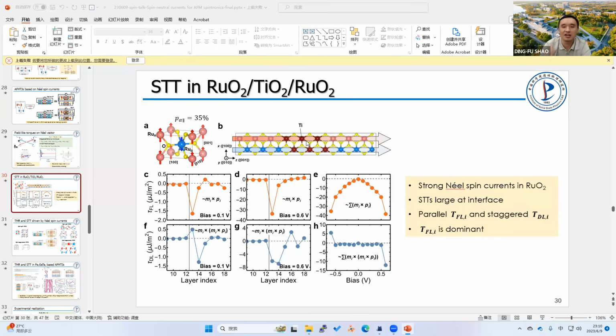In this case, I think the titanium oxide is the best, because the structure is exactly the same. The lattice mismatch is very small, so we can have a very good epitaxial structure to preserve the position of the sublattices in the two sides of the antiferromagnetic tunnel junction. If you use some other tunneling barrier without the rutile type structure, that may lead to some mismatch of the atomic positions of the two electrodes, which may weaken the effects, I think.